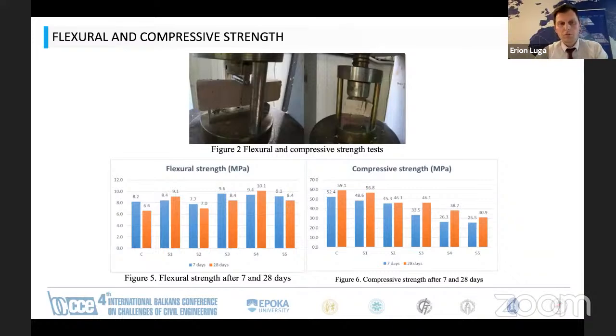Coming to the hardened properties, we performed the flexural strength and the compressive strength of the mortars. The flexural strength was performed on 40 by 40 by 160 millimeter mortar beams. On the left, we see the results of the 7 and 28 days flexural strength, which also shows an irregular trend. Actually, this is general for the flexural strength in mortars. It has a brittle failure, which doesn't allow exact results. Coming to the compressive strength, the trend is decreasing as the amount of slag increases.